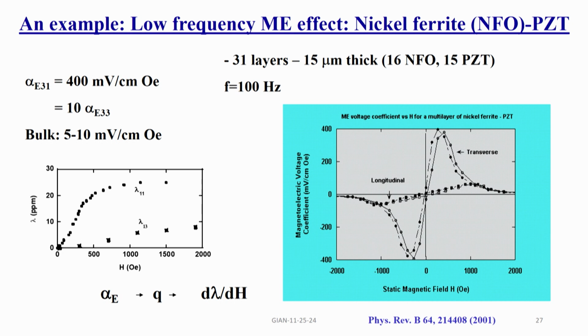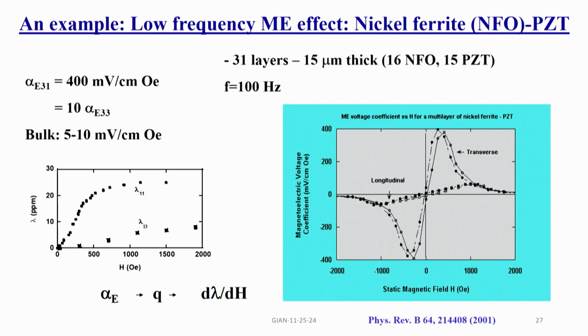It starts with 0, keeps going up and up until it peaks where the slope is maximum, then it keeps going down because you are going above this maximum slope. It keeps going down, down, and then ultimately it goes to zero when the magnetostriction saturates. This is for in-plane magnetic fields. This is for magnetic field perpendicular to the plane. As you see here, the magnitude for this case is much smaller than in-plane magnetic field. That's because when you change the orientation of the magnetic fields from parallel to perpendicular, there is demagnetization. Both the AC field and the DC field will decrease because of the demagnetizing field. So the overall effect will be weaker, and that's what is shown in this data.